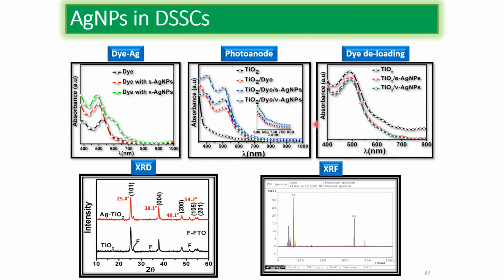I also wanted to observe whether the increased absorption is because of more thickness or some other effect, or just because of plasmonics. So we carried out a dye desorption test, where we take off the dye and again measure the absorption, and we confirmed that the dye loading is almost the same. So all the absorption I got is because of the plasmonic nanoparticles. This XRD of the TiO2 film shows that I got this improvement by applying only 1 weight percent silver. TiO2 is 99 weight percent in the film, and only 1 weight percent silver gives the maximum absorption improvement of around 35%.